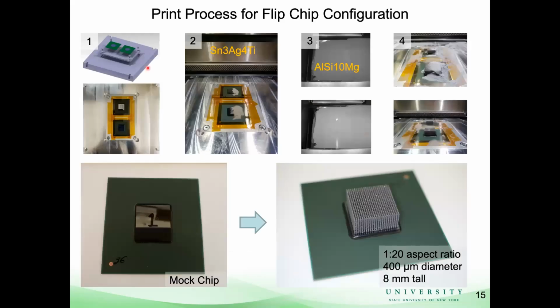So this is a general process for how we could print onto a packaged chip. We basically mount the chip into a holder that mounts the part, and then we tape up the side so powder doesn't get into the ball grid array and the solder ball array. And then we print a few layers of this Sn3Ag4Ti alloy, and then print our other material. In this case, we print aluminum on top of that.